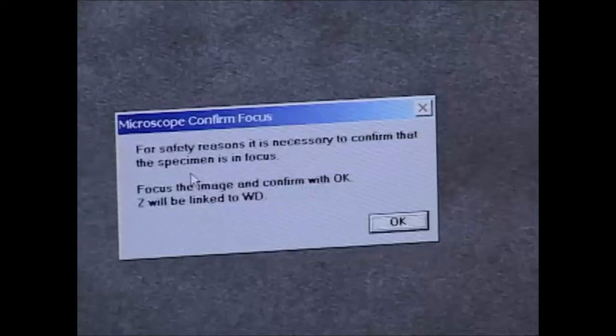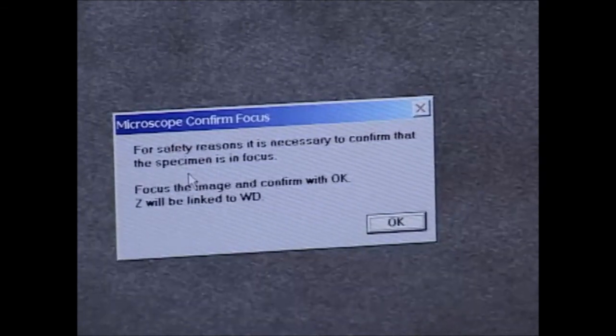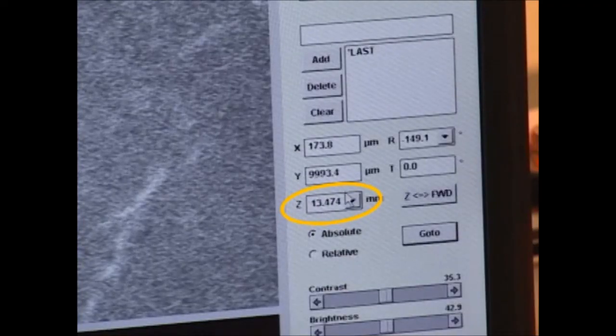And you can see that these defects in the surface of my standard here are more visible now that I've adjusted the focus. So I'll magnify one more time. I'm now at 3100, over 2000. I get the best focus I can, and now the working distance reads 13.5 millimeters. This is an accurate measurement of how far the sample is from the pole pieces. So I'm going to calibrate that height of the stage by clicking OK in this box. And you can see that it transfers the working distance into the Z coordinate over here.